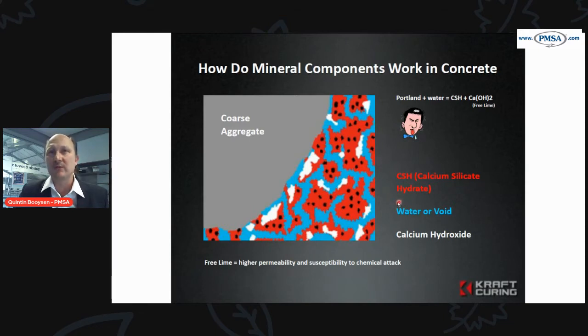And in between all of this, we have the CSH forming. We also have water, which is a free water floating around. That's the water that's sort of left over from the hydration process that's hydrating the cement. And we have a byproduct, which we call free lime. Free lime is your calcium hydroxide, which is down here.